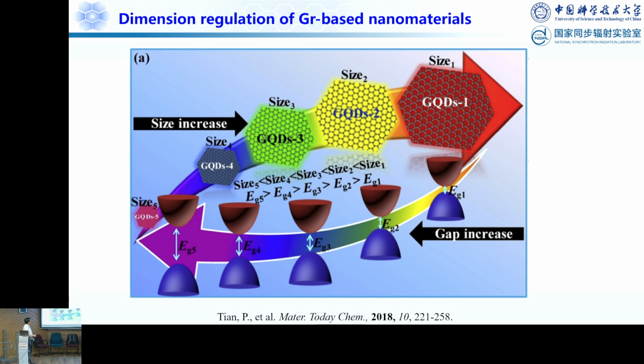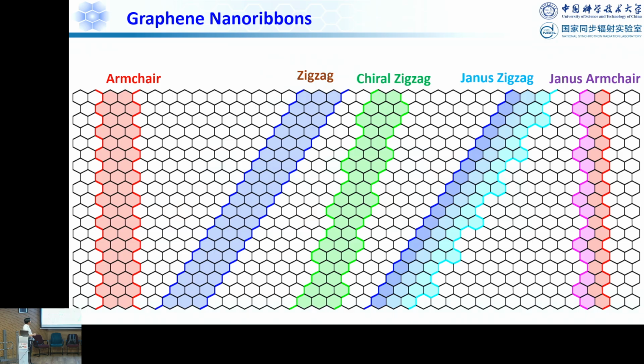So you can see these graphene nanosheets. If you reduce the dimension, you can see the band gap open. This is one example, and you can also cut the graphene into graphene nanoribbons. Here I show graphene nanoribbons with different edges. For example, armchair, zigzag, chiral zigzag, and Janus graphene. For example, one side has zigzag edges, the other side is different. And here we can also synthesize armchair Janus graphene.